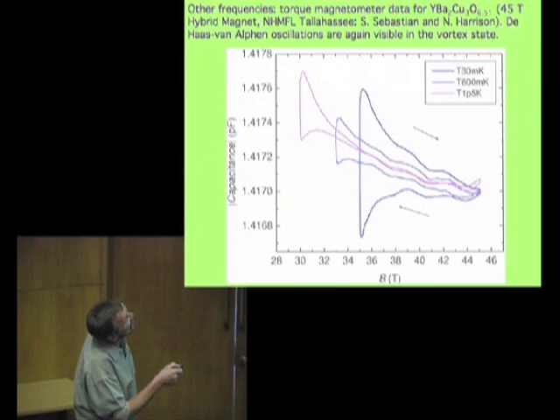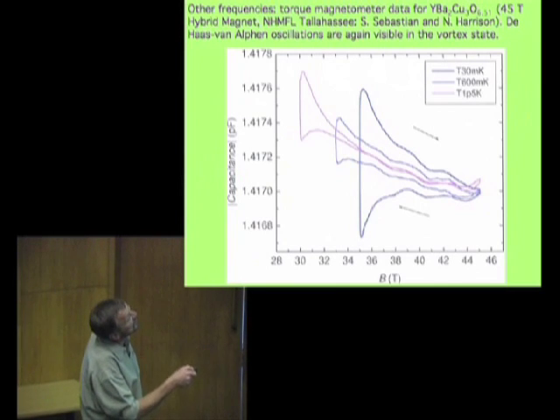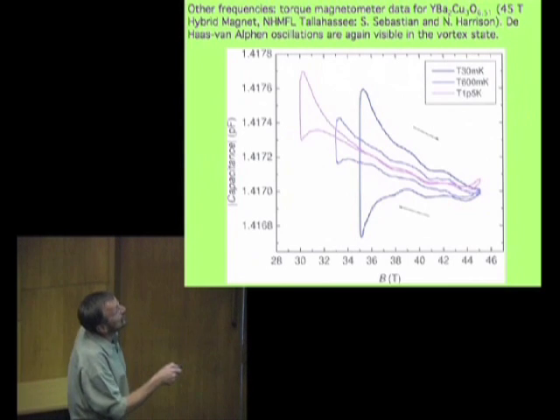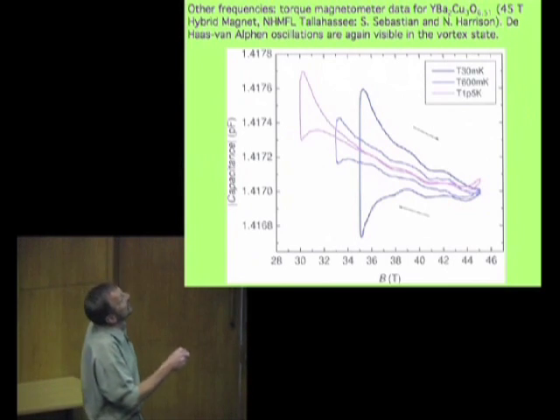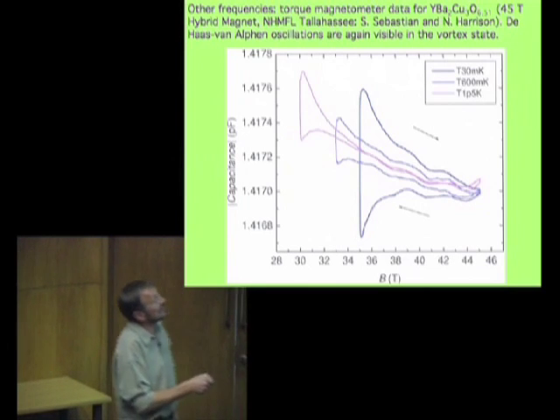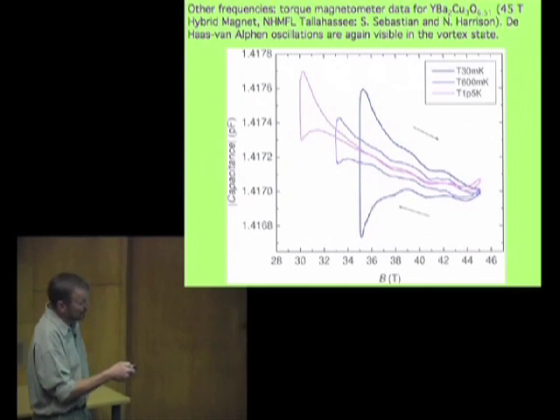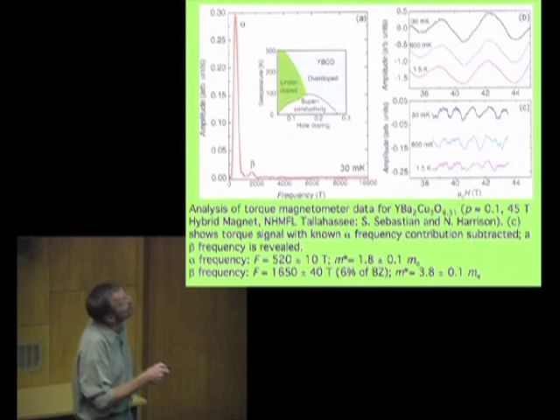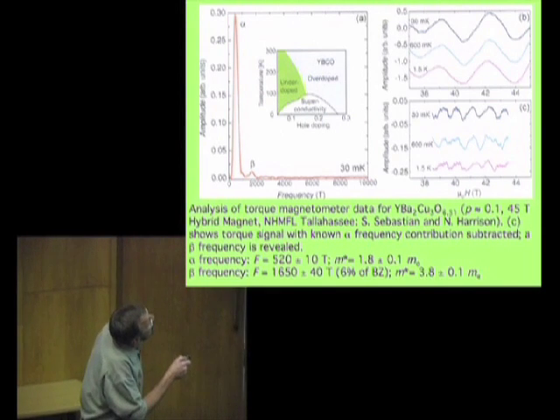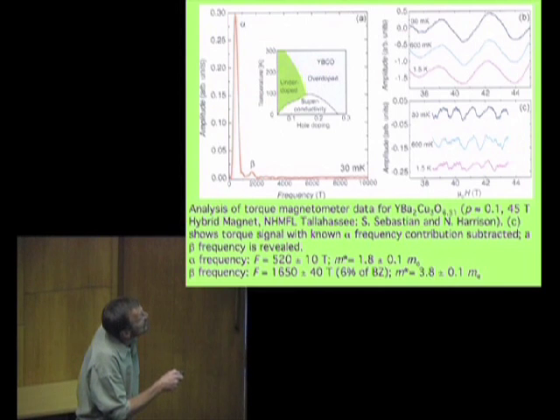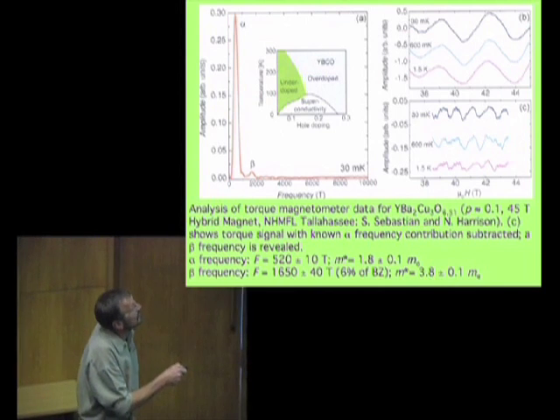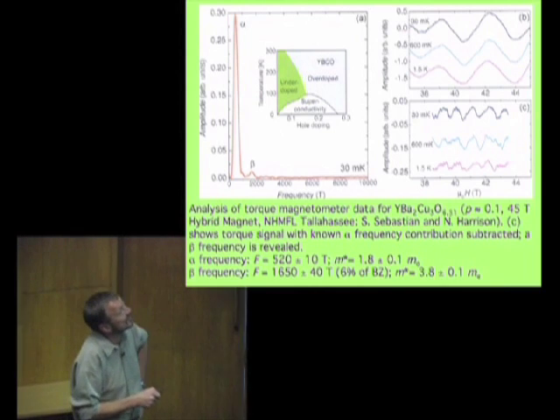colleagues of mine looked at the doping that the Toulouse people had studied again. This is the 1, 2, 3, 6.51 cuprate in the hybrid magnet at Tallahassee, and they did torque magnetometry again. These are the raw data. If you look very carefully at these, do a Fourier transform of the data, you see the frequency that was seen before at about 500 Tesla. There's an additional blip over here at about 1600 Tesla.